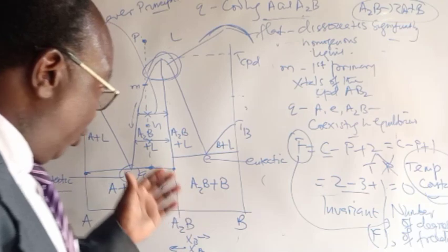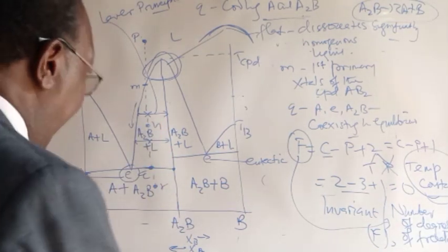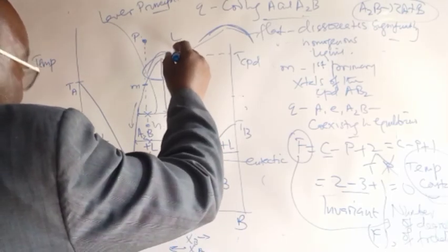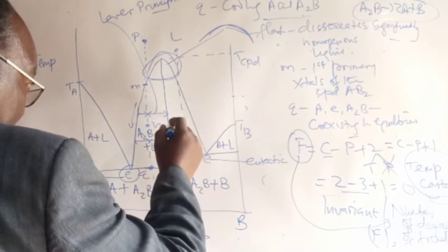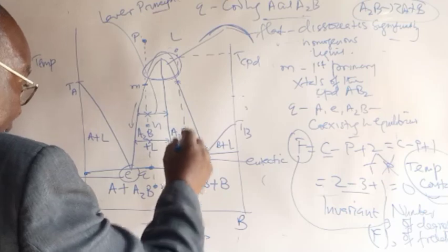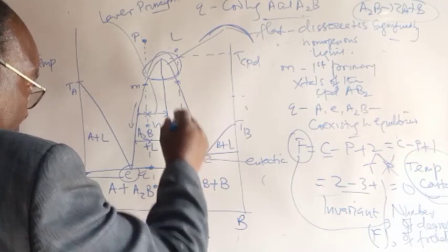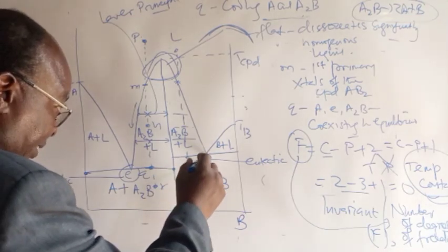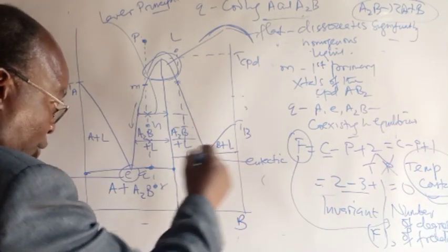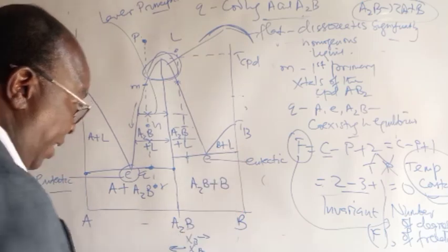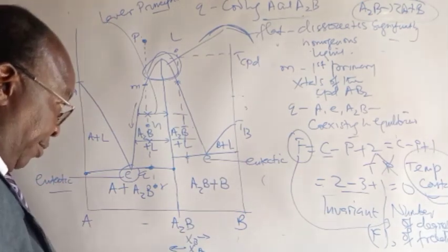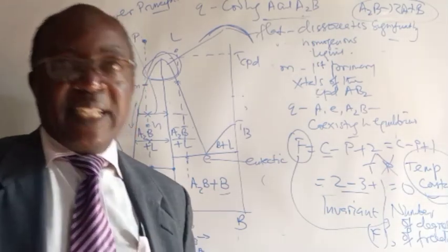And when we are at the eutectic point, even if we repeated the same thing at that particular point, even if you took another isopleth, the story would be the same. That is, you still have the first primary crystals of A2B and liquid. As you continue, the relative amounts obey the lever rule. At this point, there are three phases coexisting in equilibrium, so it is invariant. Temperature change will be halted for some time, and then again you start cooling those two solids. So let us stop at that point. We'll pick up with other thermodynamic lectures.